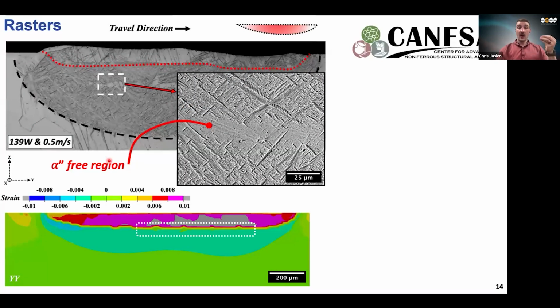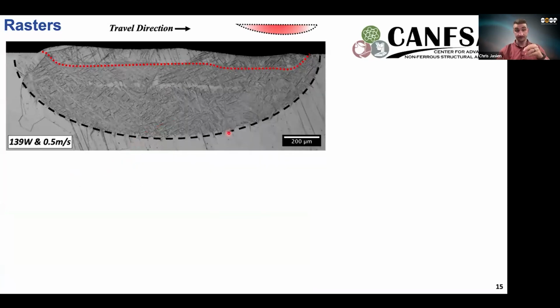And so when we dive into the models, the cause of that is, as you transition from tensile stresses in the melt pool to compressive stresses, you get this balancing point, this zero stress point, which is what this correlates to, where there's not enough stress. There's zero or very limited amounts of stress to actually cause this transformation to happen. So these models were able to reveal and show this to us.